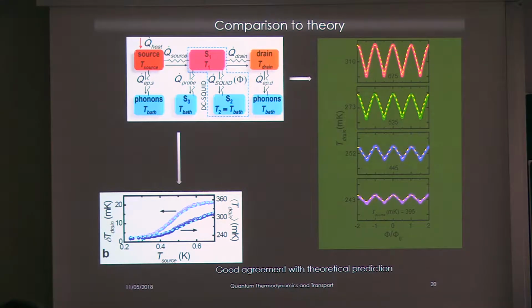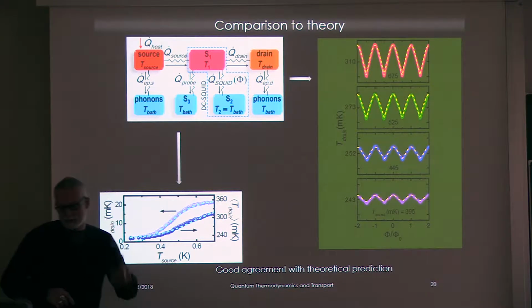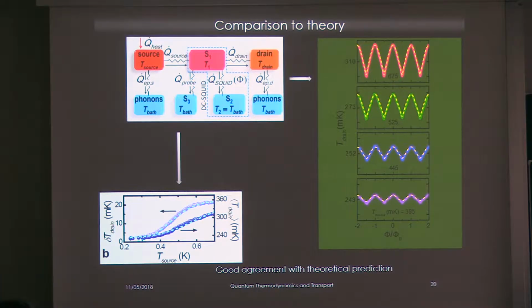As a result, we can obtain the electronic temperature in the different parts of the structure and then make the comparison with the experiment. So for instance, in this case here, the yellow line is the result of these equations, at the steady state with the parameters extracted from the experiment. And so you see that there is a pretty nice accord with the experiment, okay. So this shows that all this transfer Hamiltonian approach that was envisioned by Maki and Griffin in '65 indeed works pretty well, and indeed there is the existence of this effect. So this can predict very well and model very well the thermal Josephson effect.